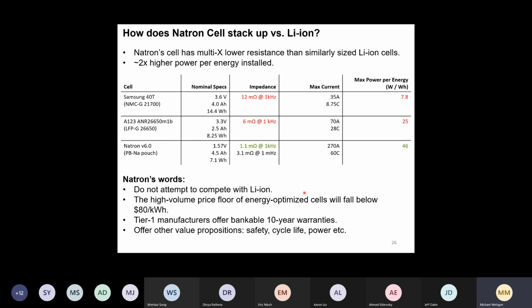And so how does it compare to lithium ion? So the resistance in these cells, which is measured by impedance spectroscopy, we also heard this in class, is quite a bit lower than in other lithium ion cells. So this table shows an NMC graphite cell, an LFP graphite cell, and the Natron energy cell here. So we see in the specs the average voltage, the capacity, the product of these two gives you the energy of the cell.